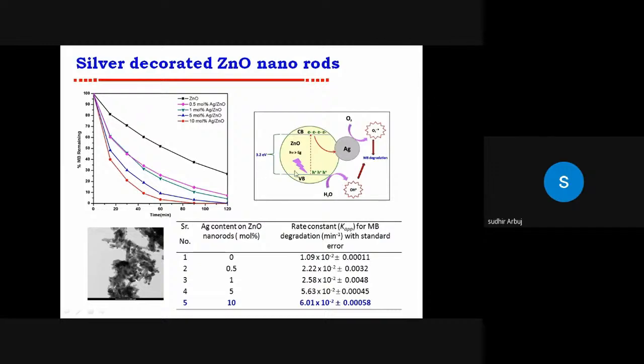So this is the general mechanism of why this activity increases. As soon as the electron-hole pair is generated, the electron is absorbed by silver and it is used for the further degradation reaction. We are also finding the rate constant values, that means a chemical kinetic study by plotting ln C0 by Ct versus time. We are getting the chemical kinetic rate constant for 10 mole % silver of almost 6.01 into 10 raised to minus 2. This is almost 6 times more than pure zinc oxide. See, the reaction rate is 6 times faster as compared to the pure one.